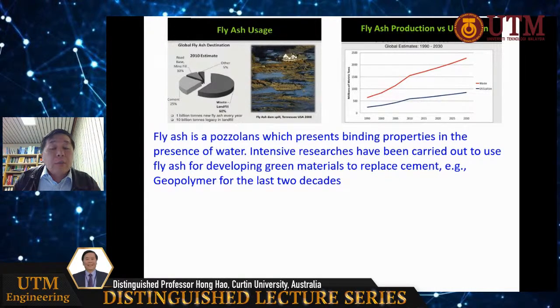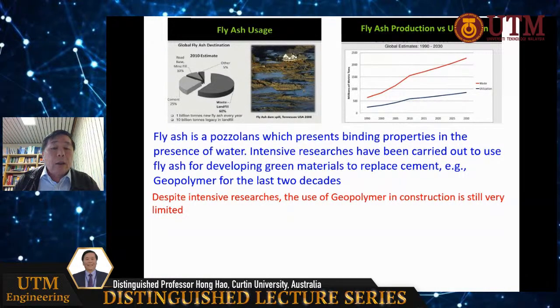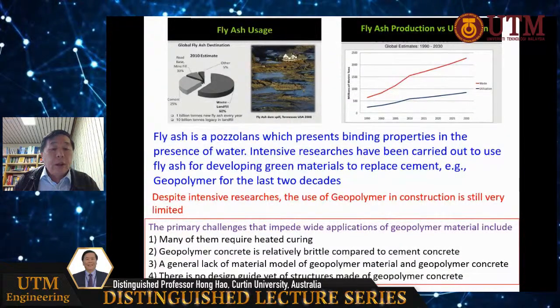It was first proposed in the 1970s, but intensive research started by the late 1990s, around year 2000. Much research has been conducted, but the application is still quite limited. Of course, I summarized a few reasons. One, many of them require heat curing. It cannot be cured by ambient conditions; normally it is cured at a temperature of 70, 80 degrees. On the construction side, of course, it's difficult to heat cure the concrete. But if it's prefabricated in the workshop, it should be okay. Or we can develop a material which does not need heat curing, with ambient curing.